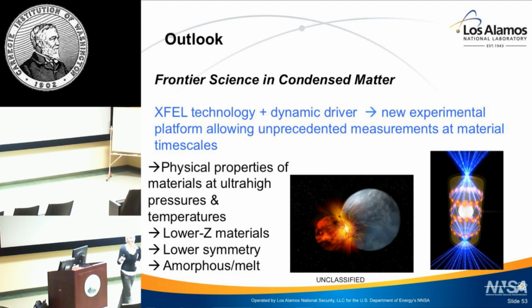That's an excellent question, and it's a direction that we want to go. So part of the stepping stones here, we started with the simplest case, the fused silica, SiO2. Then we went to crystalline, so quartz. Again, pure sample, single crystal, right? We also have data, which I did not show, on a natural sample. So the natural sample pulls in grain boundaries. It'll also pull in some porosity. So having some distribution in porosity in your sample will actually kick you off the Hugoniot a little bit. It'll be a little hotter, right?